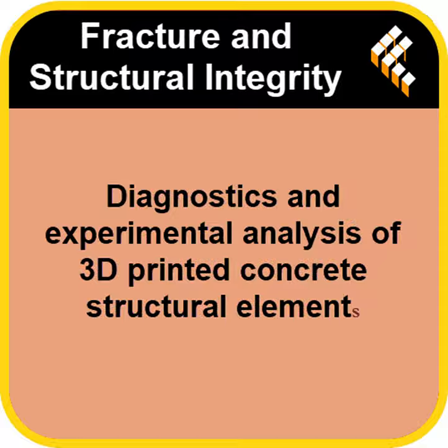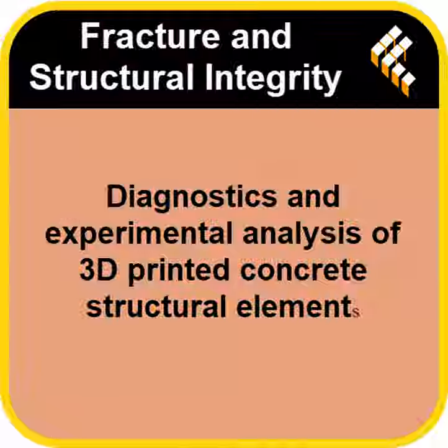That's what concrete is famous for. On that front, the anisotropy was much less pronounced. The average values were around 25 megapascals, which is perfectly acceptable for structural grade concrete. So compression is mainly about how dense the material is locally. It seems to be, yes.